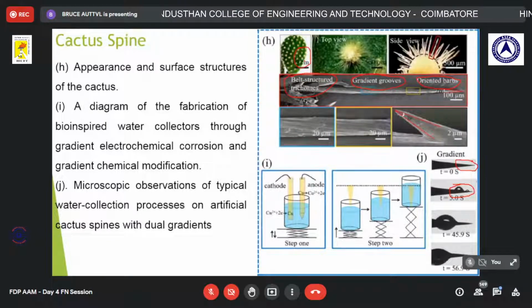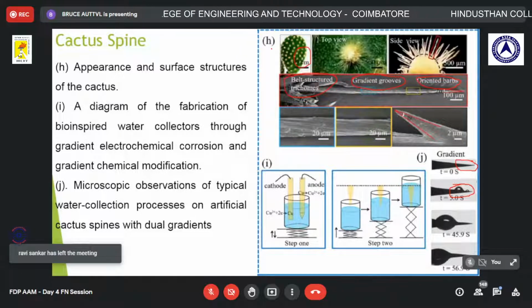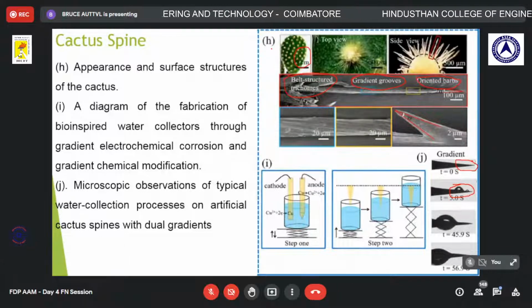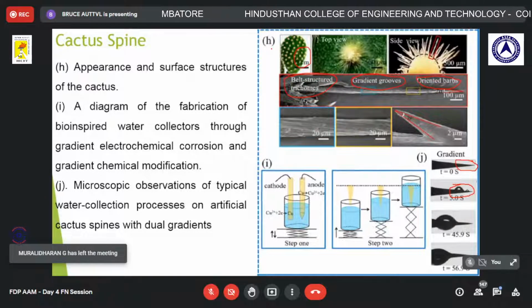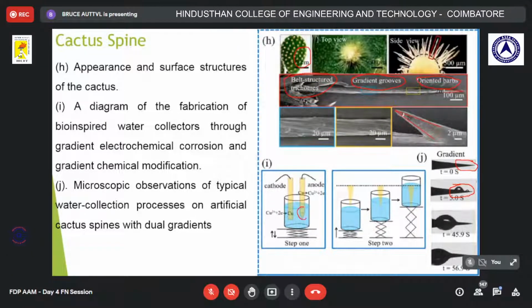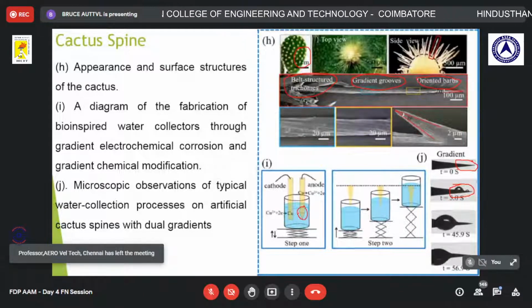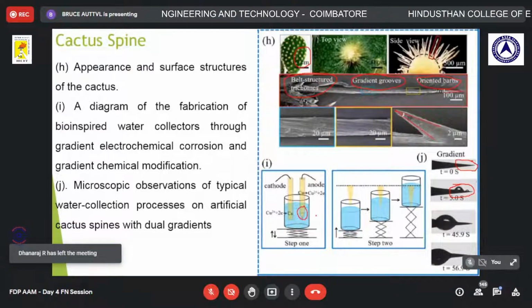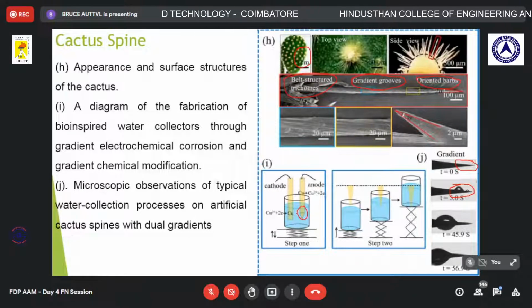That is the thing, and you can see a simple experiment also here. It is developed based on the bioinspiration of the water collection principle of cacti. It is designed as a bioinspired water collector with dual gradients. You can observe cathode and anode here, with gradient electrochemical corrosion and gradient chemical modification. Okay, gradient electrochemical corrosion and gradient chemical modification processes are involved. The artificial cactus spine, here you can observe, collects water, and it is reported that the water drops are collected at a relatively high speed of about 2.08 microliters per second, and it transports them quickly with a velocity of around 20.5 micrometers per second.